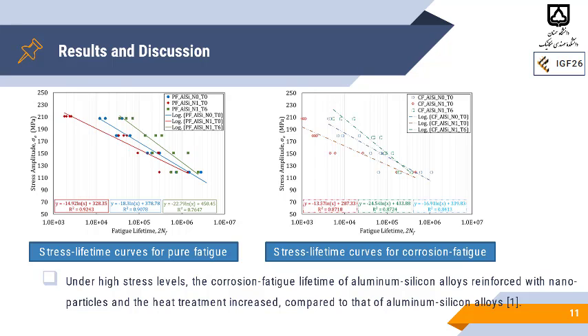So under high stress level, the corrosion fatigue lifetime of aluminum alloys reinforced with nanoparticle and heat treatment increased compared to the base material. This result can also be found in the literature, reference number 1.